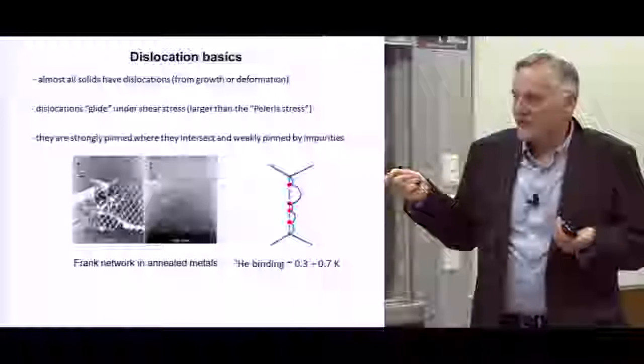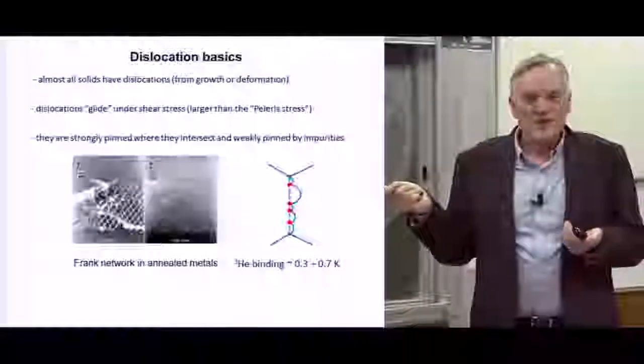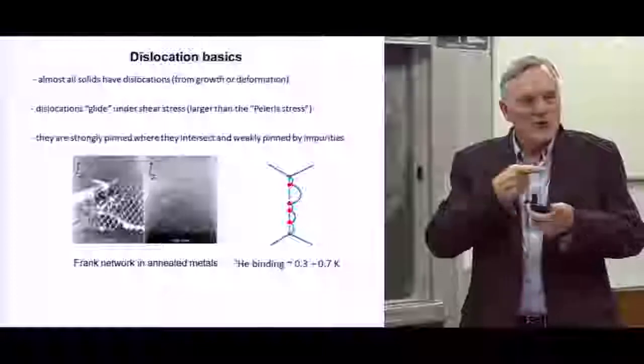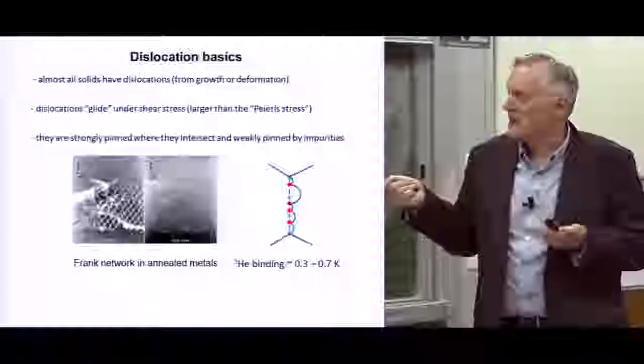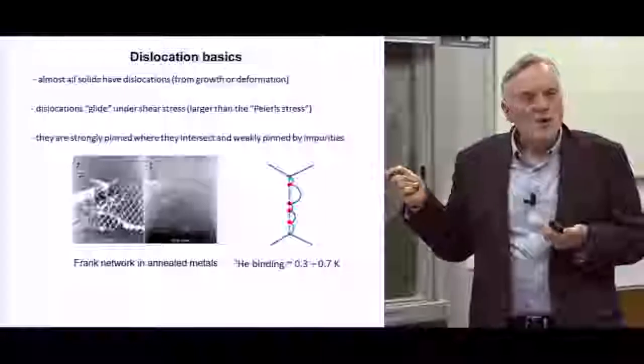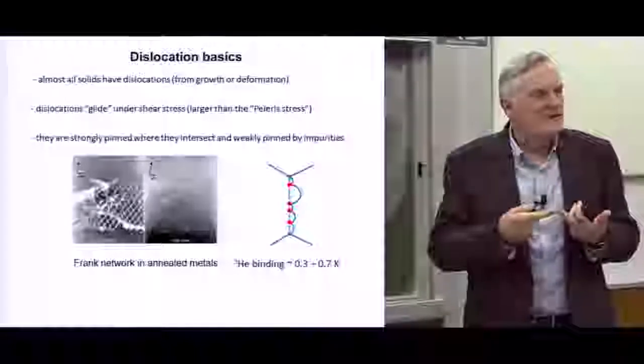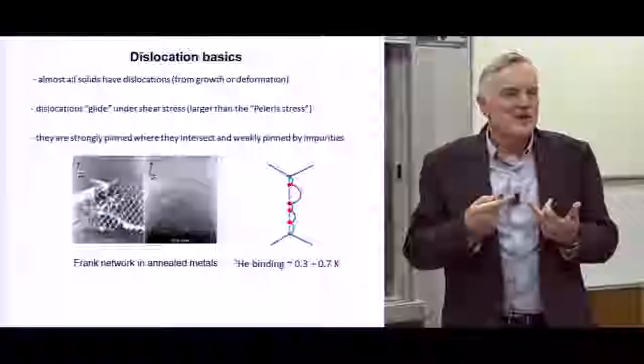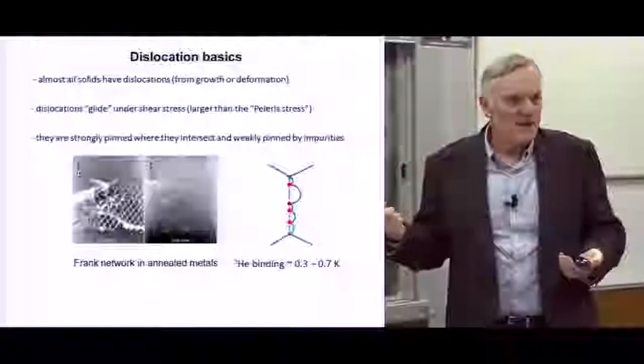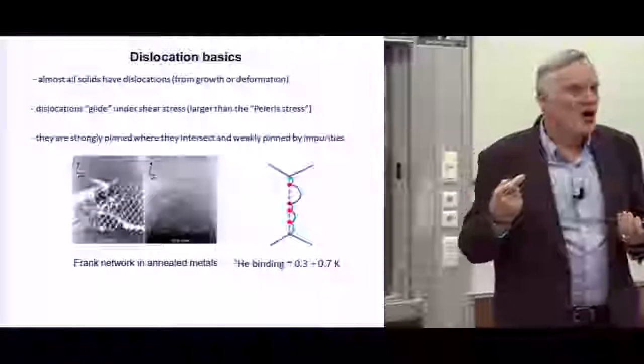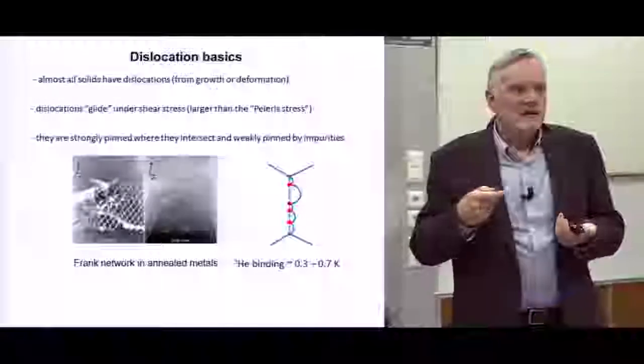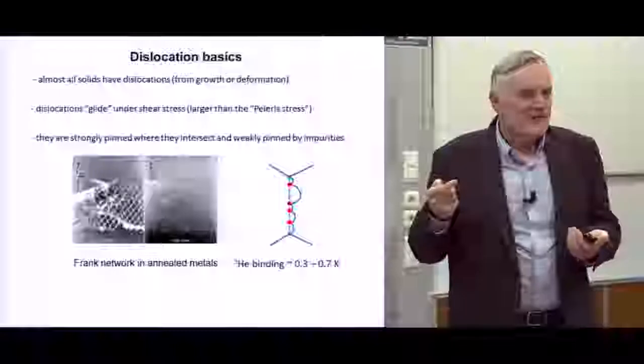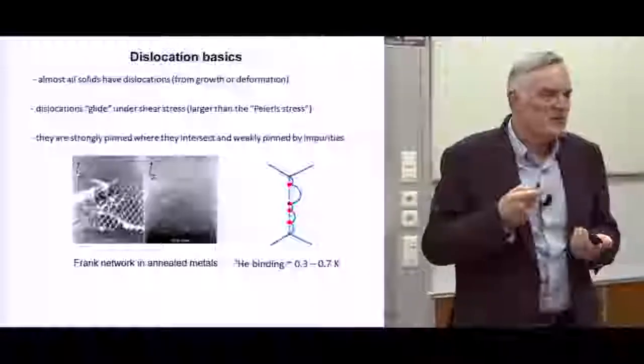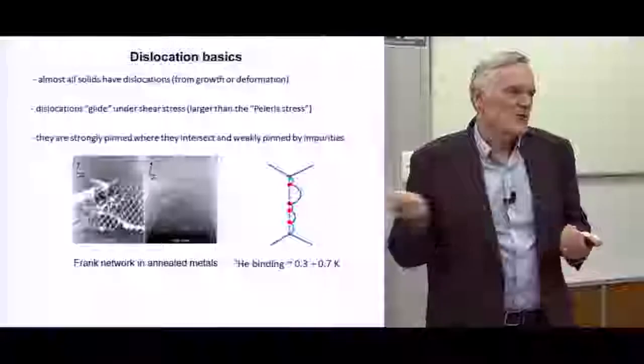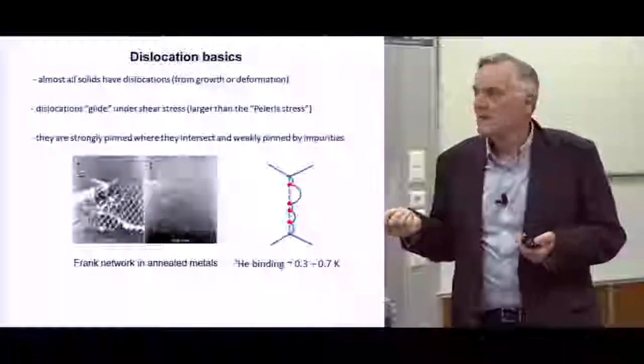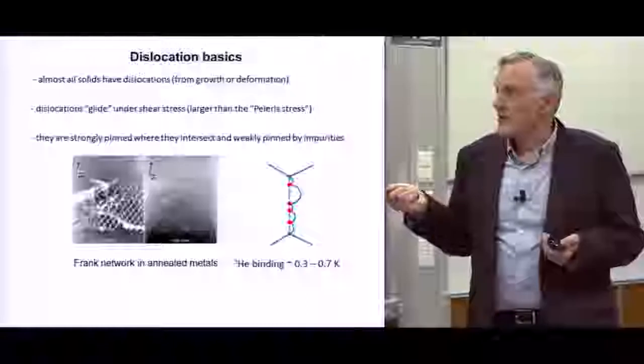Another thing people know from metals is that if you anneal a crystal a bit and look at them, they form a network. They're not all random. Where they intersect, they're very stable. You get a stable network. And you also know that if you put impurities or inclusions in, they tend to immobilize dislocations. They bind onto them, immobilize them, and quit affecting the crystal. For example, if you take copper, it's very soft, dislocations move. The more care you take in making copper, the softer it gets. But if you put 0.5% or 1% of beryllium in it, it becomes hard like steel. Or if you want carbon steel, you put carbon in it to make it hard. It's because it immobilizes dislocations by binding and pinning.